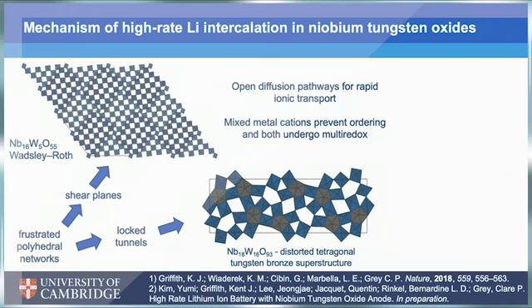Now, the structures of the 2 phases are quite different, but they have some common themes. And the thing that really provides the structural stability is what I'll call a frustrated polyhedral network. So in the crystallographic shear structures, they've got the shear planes that prevent the sort of twisting and tilting that you would expect in a perovskite structure if you tried to put lithium in, which would clamp down and really decrease the rate. And in the bronze structure, there are these locked pentagonal tunnels that, again, prevent you from having structural distortions that would be harmful either for cyclability or for rate.